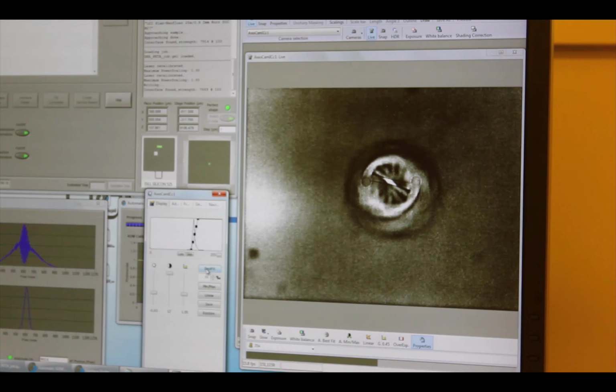And once we're happy with it, once we do some power tests to make sure that we're using the correct laser power and we're not burning the material as we're printing it, or if there's not enough power, then we just won't get any polymerization at all and we just won't get the structure. So once we optimize all those parameters, we're done printing and we can take it out and stick it in something called a developer. So the developer, what it does is it just rinses away all the material that hasn't been polymerized. So all that liquid resist honey material is going to be gone afterwards, and we're just going to be left with the final structure.